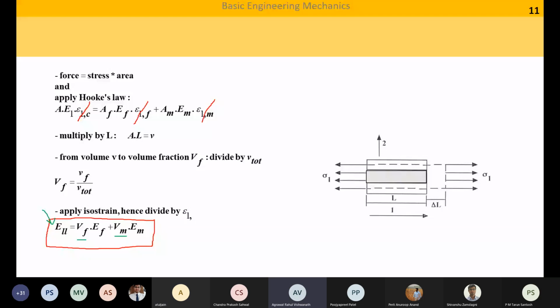So we will add that term to this. Yes. So you are going to just say plus VF prime times EF prime, where VF prime is the volume fraction of the second fiber and EF prime is its modulus, and always this condition has to be satisfied: VF plus VF prime plus Vm is equal to 1. As long as this condition is satisfied, you can calculate the effective modulus even if there is more than one type of fiber. Those composites which have more than one type of fibers are known as hybrid composites.